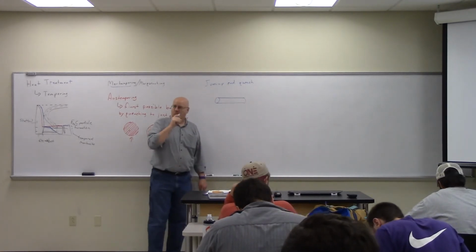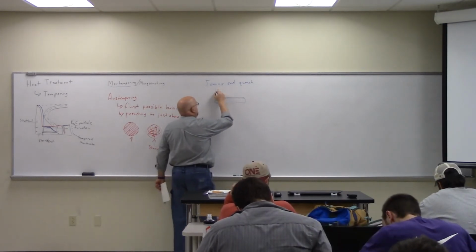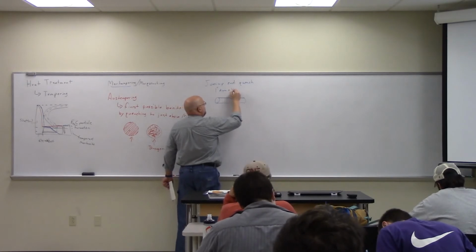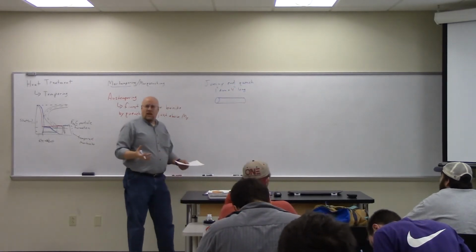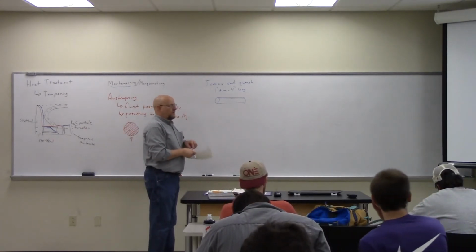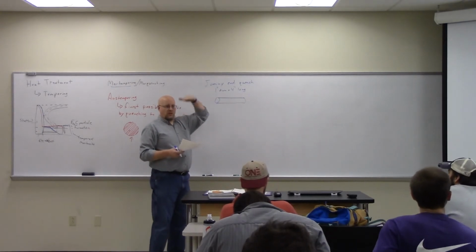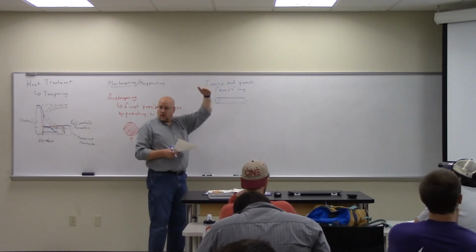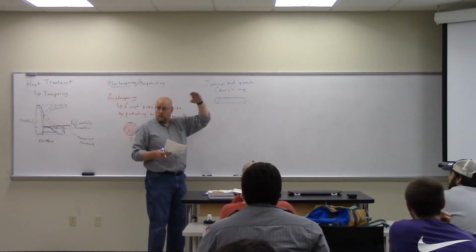Okay, so it's a round bar with just a flat surface on the top. And again, 1 inch diameter, 4 inches long. What I do is heat that thing up to a particular temperature, some kind of austenizing temperature. Remember, gamma is called austenite. So an austenizing temperature is anything above 727 if it's eutectoid steel, so that I get it up to be pure gamma, and let it sit there long enough to get completely transformed.